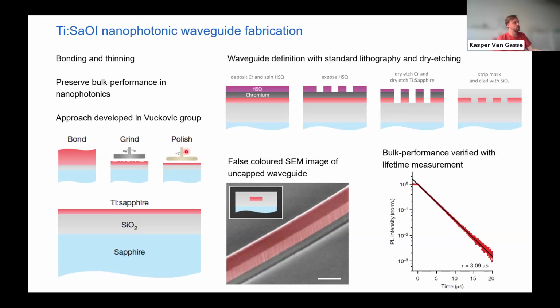Now, of course, we did this approach to enable very high quality crystalline material in a thin nanophotonic film. But of course, once we make the waveguides, we do have to verify that the bulk qualities of the sapphire are preserved. And this we did with the fluorescence lifetime measurement. And we clearly saw that indeed the fluorescence lifetime is about 3.1 microseconds, which is fully within what we expect for bulk at this level of doping and crystallinity. So this process really does preserve the pristine bulk qualities of the crystal, even when you go to nanophotonics.